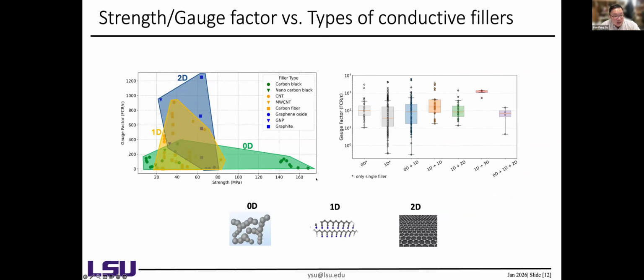Then we also organized this data, and we found the conductive filler can also be classified into 0D, which is a powder form, 1D, the fiber form, and 2D, like the plate. We found that 1D and 2D seem to be better compared with 0D, so we collected the materials for 0D, 1D, and 2D, and tried to make self-sensing concrete and see what results we can obtain.